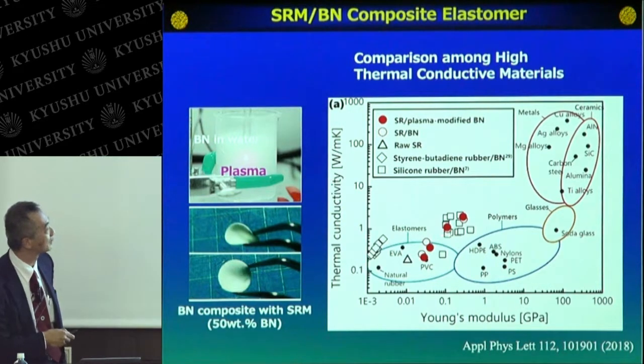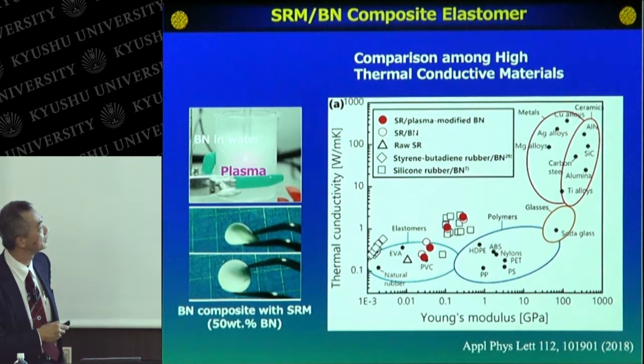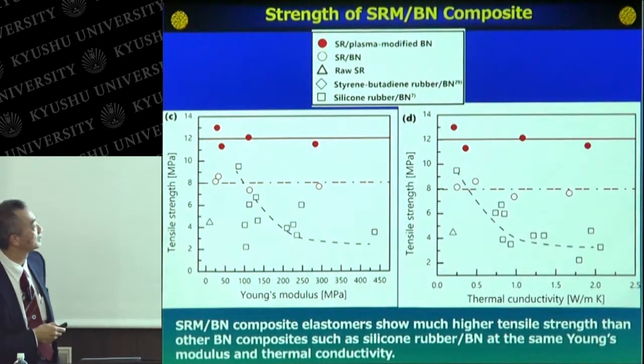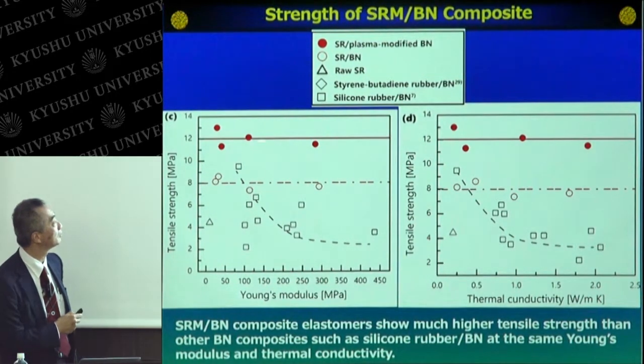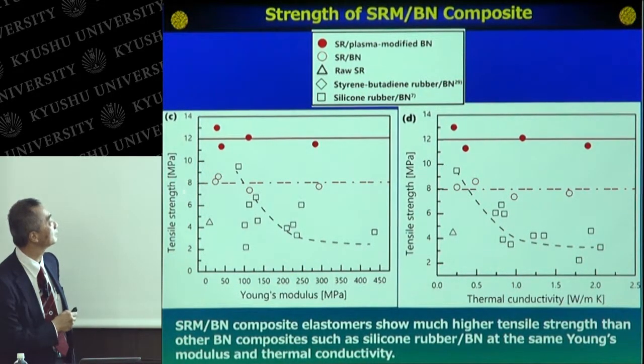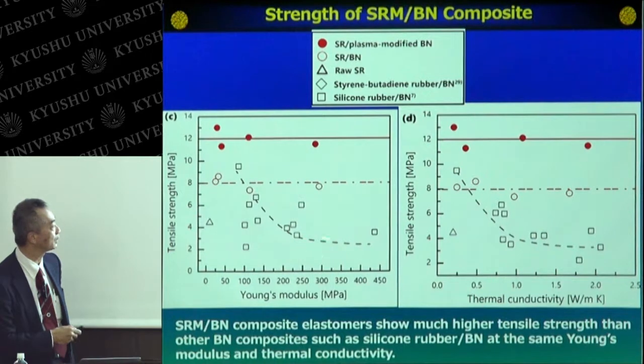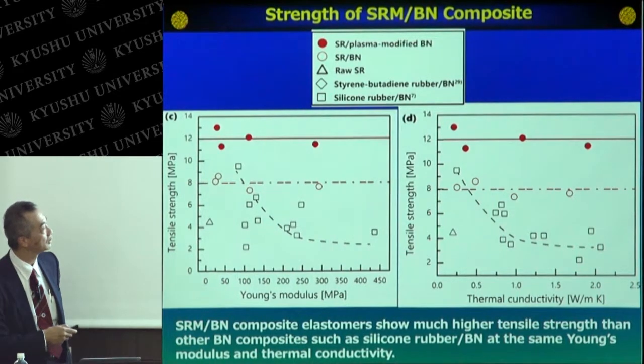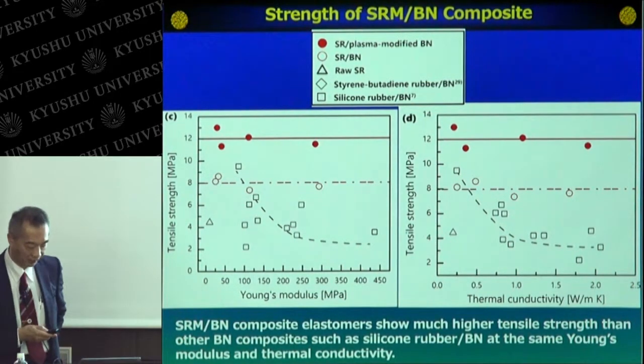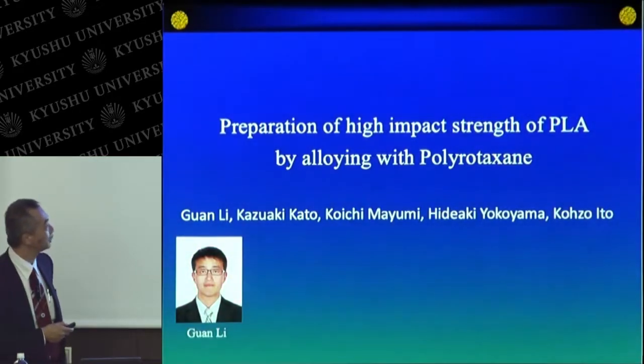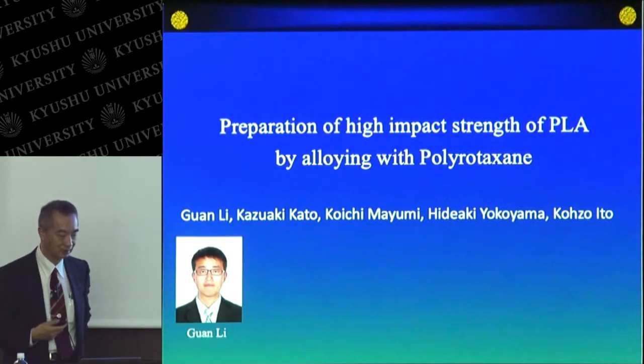And this level is almost the same as the silicone rubber boron nitride system, but the tensile strength is quite different. So this red circle shows the tensile strength of the sliding materials. And this open square shows the results of the usual silicon rubbers. So you can see the sliding material, sliding rubber shows the higher tensile strength compared to the usual silicon systems.